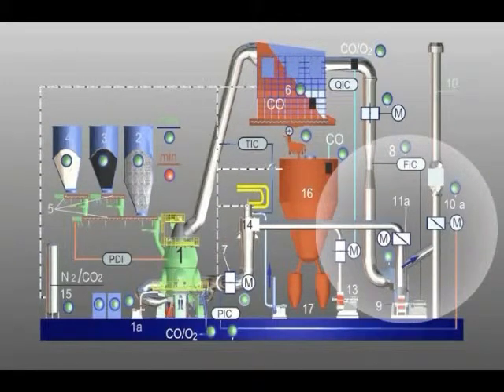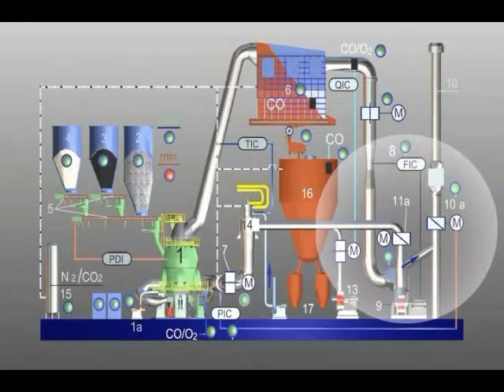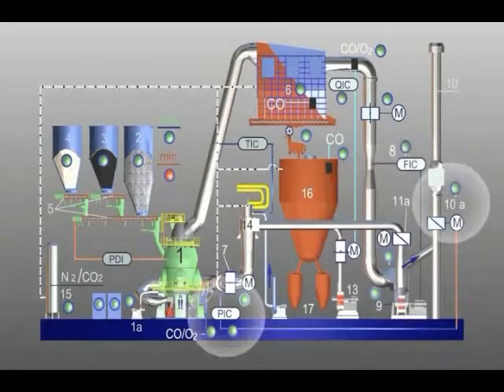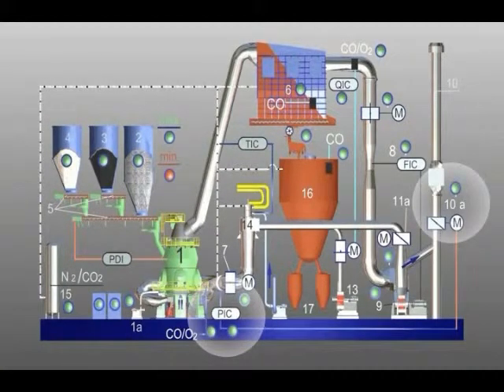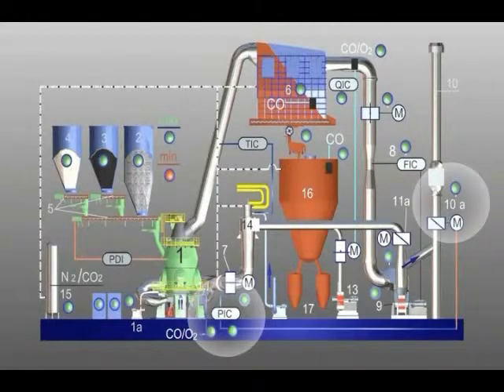The volume flow of process gas is measured via a Venturi tube, position 8. This volume flow is regulated by means of the vane control, position 9. The volume flows of process gas within the system are regulated via suction pressure control. The controlled system consists of measuring the suction pressure before the mill and the regulating flap valve for the exhaust gas flow in the stack, position 10A. The set point on the pressure regulator, PIC, before the mill is usually set to a value of around -3 millibar.